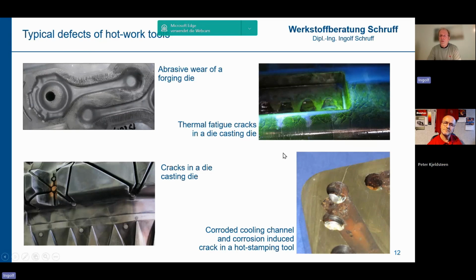Yeah. So the aluminum picks up that shape of these cracks, and you will find the traces of the cracks on the cast component. That is for many applications not a problem when you think of a gearbox or transmission housing, a clutch housing of a car. Nobody cares for visible traces of these cracks. But the problem is that these cracks grow into the steel and they might lead to particles breaking out or even total cracks going into the cooling channels.